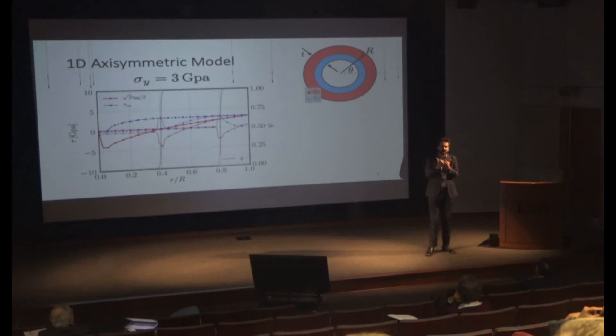I yield first because of the high compressive stresses made on the surface. But as the phase moves in, those compressive stresses create tensile eigen plastic strains in the other direction. The core has moved in, so now I'm getting tensile stresses on the outside and I can yield again.